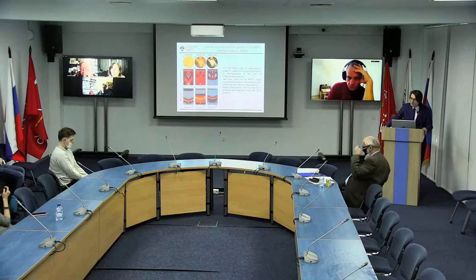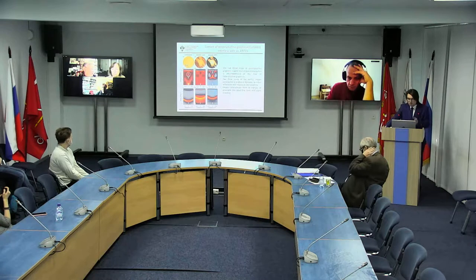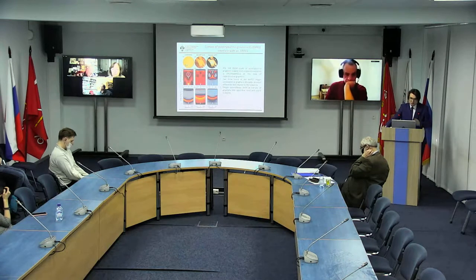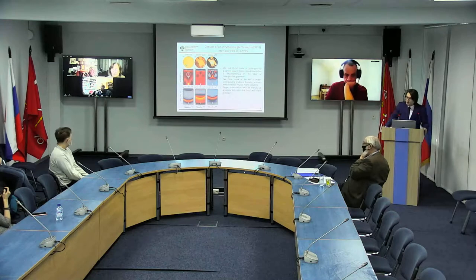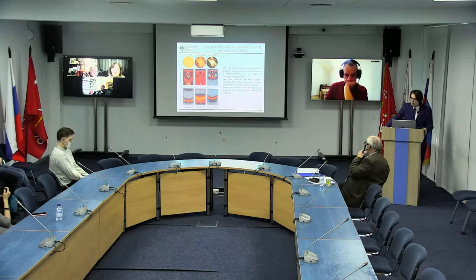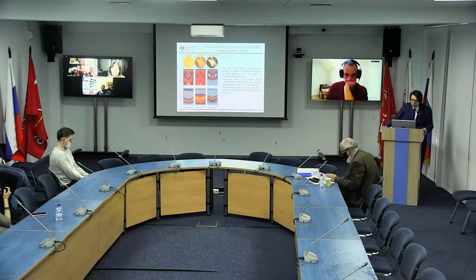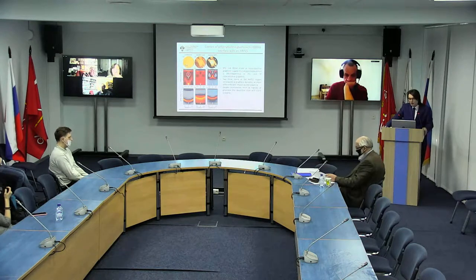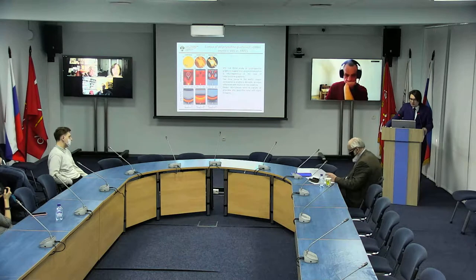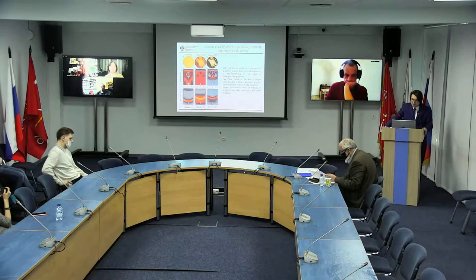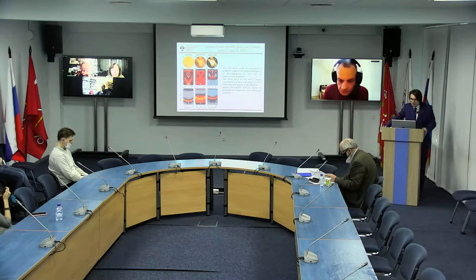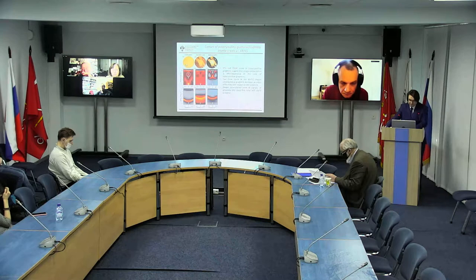And in order to visualize the intercalation, we used photoelectron microscopy. And these pictures are given on the slide in the upper part. And what can we say? Intercalation happens quite heterogeneously. These dark areas correspond to intercalated graphene that shifted to quasi-free state, and the light areas are bound areas. And the intercalation is supported by the fact that the Dirac cone, after the impact of oxygen on the samples and further heating, is restored near the Fermi level. That demonstrates that graphene shifts to quasi-free state.